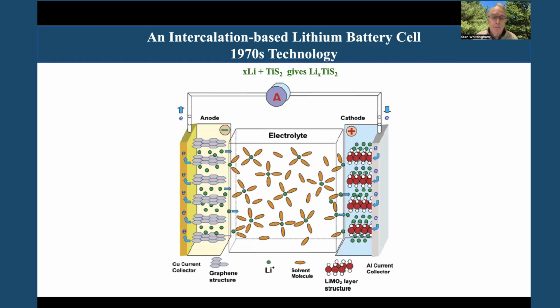So all these are based on what we call intercalation chemistry. This is where we intercalate guest species, in this case, these lithium ions, into a host lattice. Here I show you graphite, and on this side, it's a layered oxide or a layered sulfide. So the structure of these host materials does not change, except for maybe a slight expansion. So your ions can go in and out thousands of times without destroying the structure. And this is what we mean by an intercalation material.